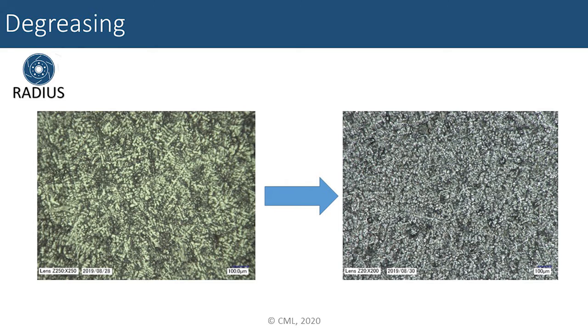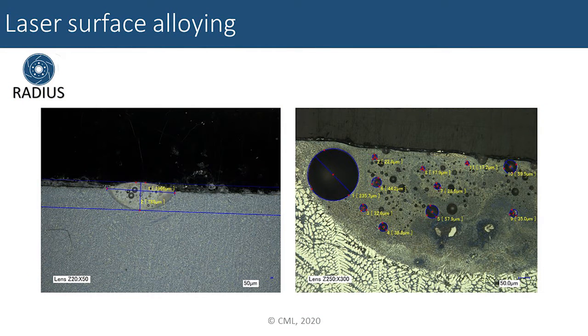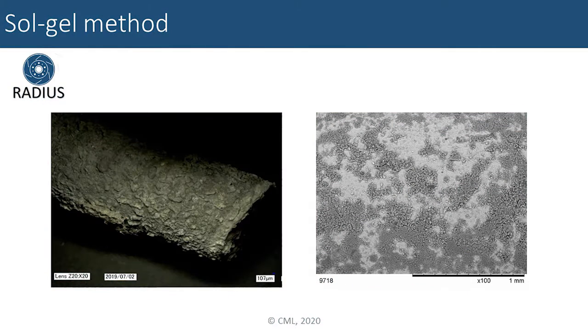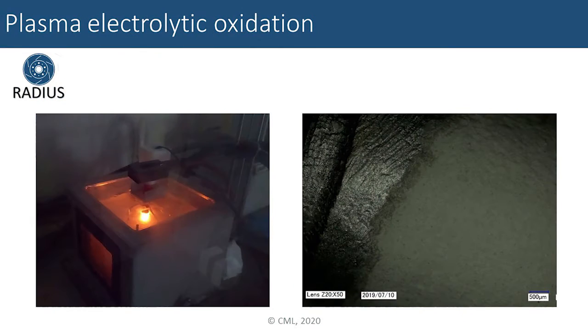Before we start the coating of the samples, we have to degrease them so the surface treatments can be effective. During the laser surface alloying method, we used a CO2 gas laser with a 5-axis CNC. The aim of this method was to melt together the prepared hard metal alloy powders with the base metal. The sol gel method used aluminium isopropyl oxide as a precursor to form an oxide layer. The plasma electrolytic oxidation used high voltage to treat the surface of the samples.